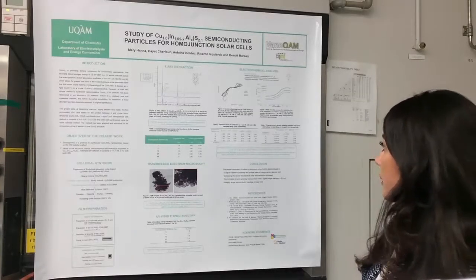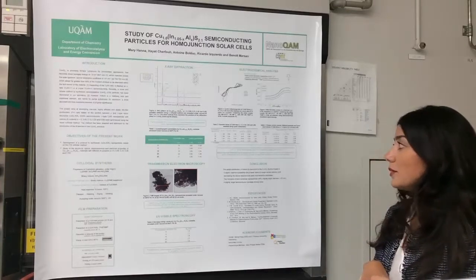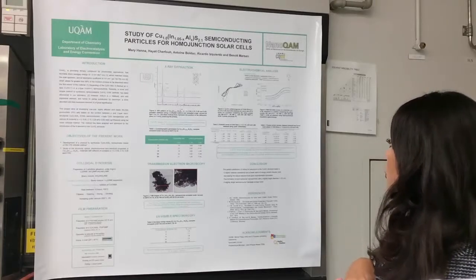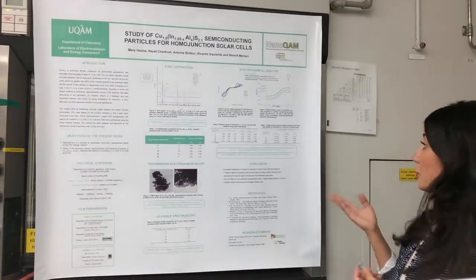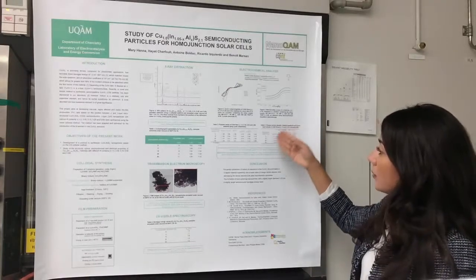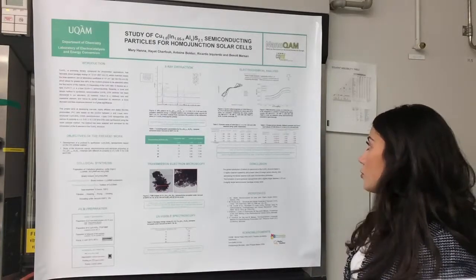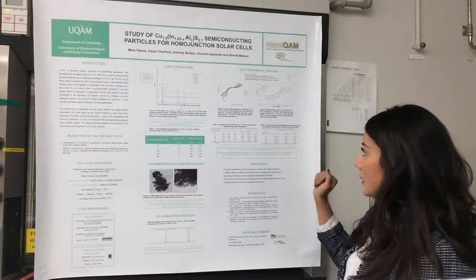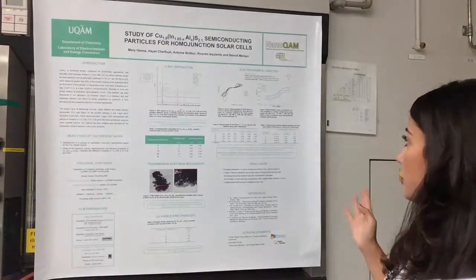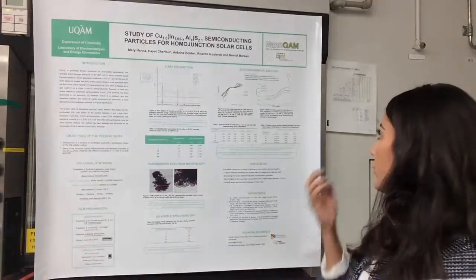For the impedance spectroscopy, we confirmed first that it was an N-type semiconductivity, and the films showed that the partial substitution of indium for aluminium leads to a beneficial decrease in the charge carrier density. As much as we add aluminum, the charge carrier density decreases, from 10^19 to 10^18, which is a big difference. For the flat band potential, we don't see any trend with the aluminum content, so we can't say much about this.